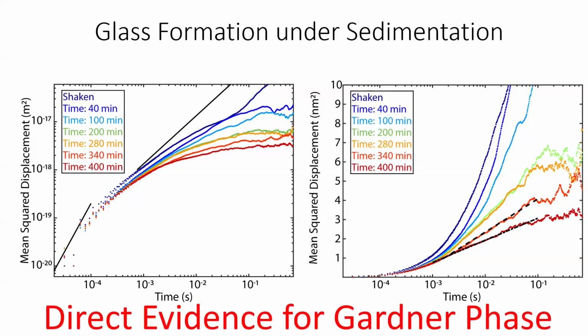So the claim would be that this constitutes direct evidence for this Gardner phase, that we have gone into a stable glass here where we hit a plateau. And then as we continue to sediment, this stable glass falls into the marginal phase.